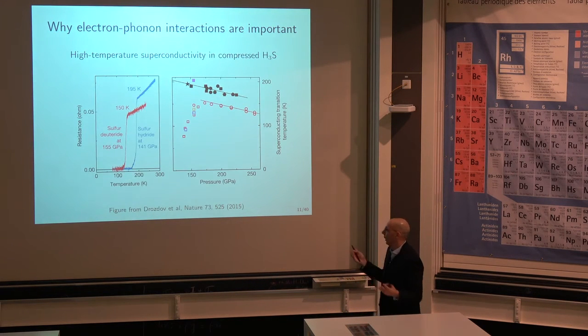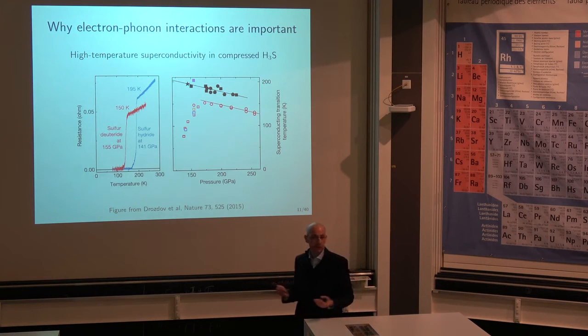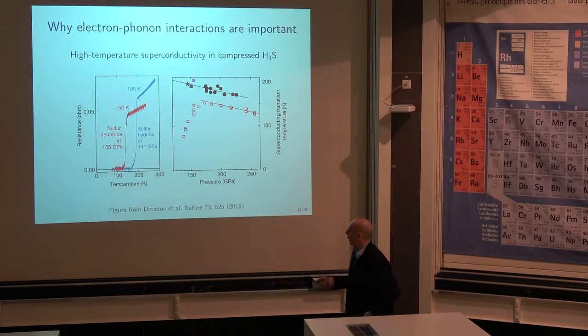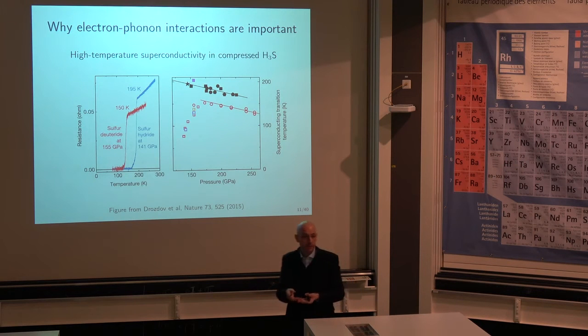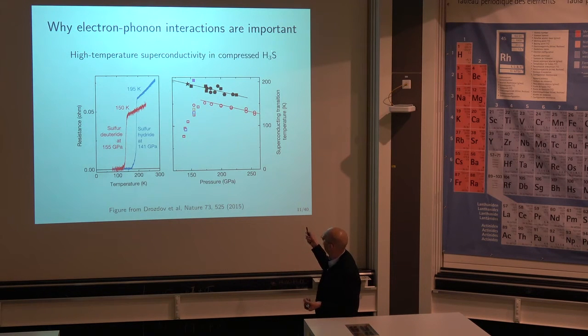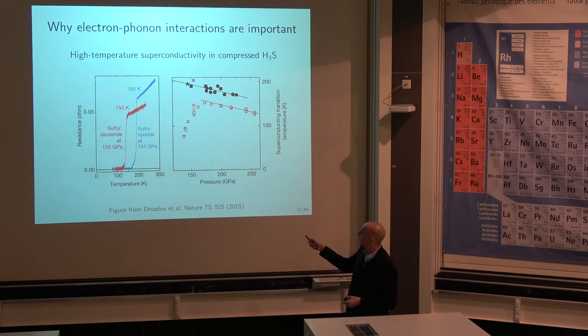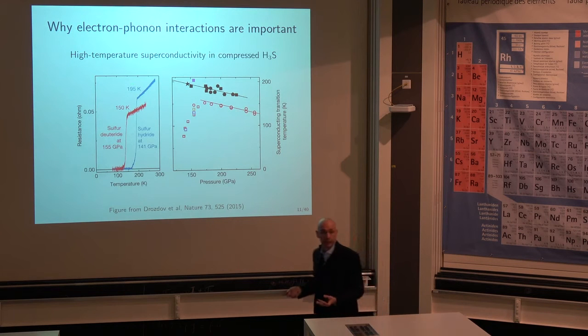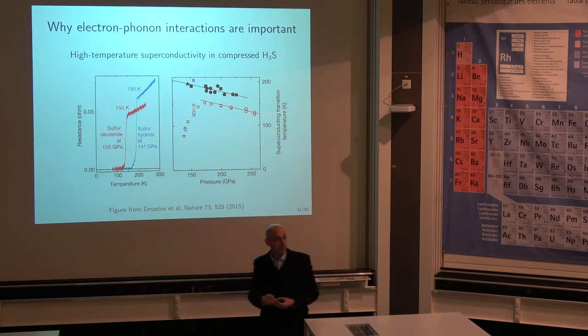And then maybe the most spectacular manifestation of this effect, as we know, is superconductivity. So I just put the most recent record. This is from high-pressure experiments on sulfur hydrides. So basically, these are diamond anvil cell measurements of this compressed sulfur hydride at around 150 GPa. So this is a very difficult experiment. But the main observation here was that when this becomes solid, it is a metal. And as you cool the system, at some point, the resistivity drops to 0. And the transition temperature in this case is about 200 Kelvin, okay? So this is the superconductor with the highest critical temperature.